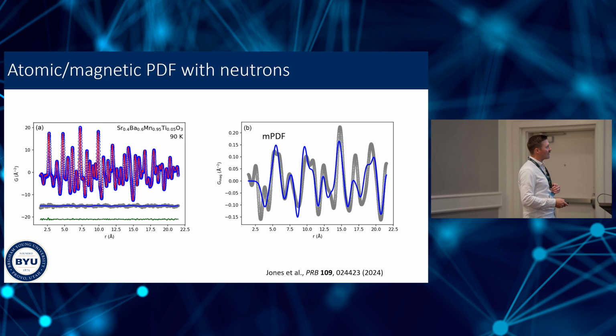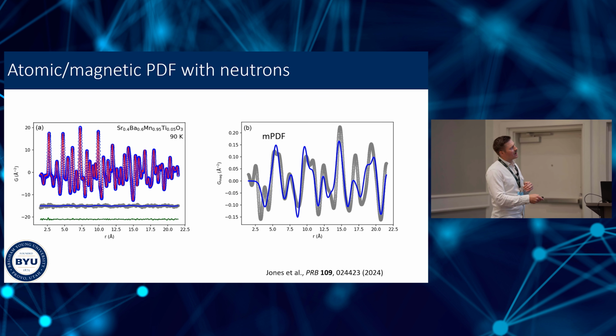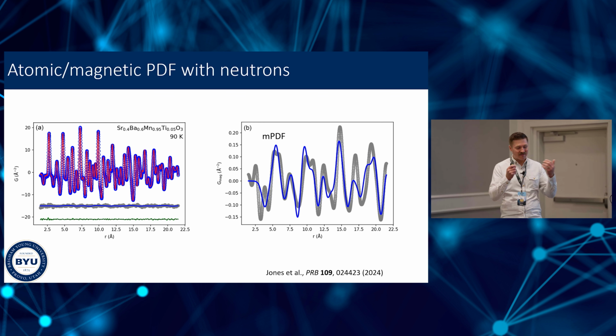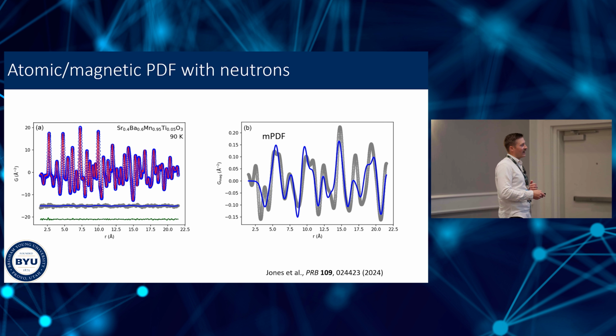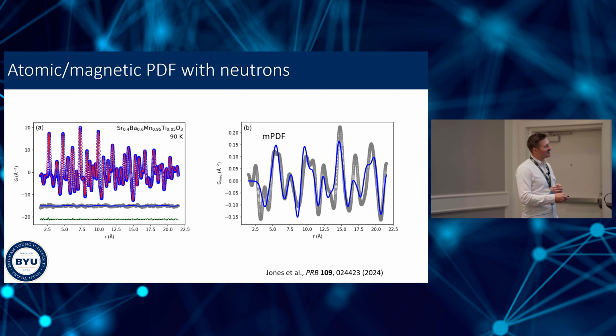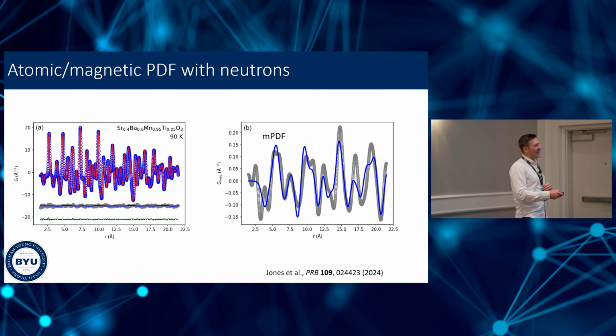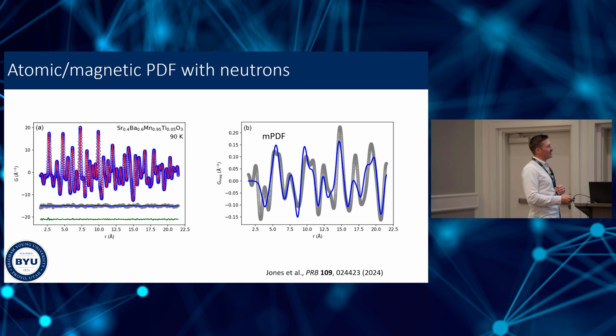Let's prove that more directly by looking at magnetic PDF data. Here's our neutron PDF data for one of the compounds that we looked at. The magnetic PDF signal is actually very small. If you're not looking for it, you won't notice it. So you have to work kind of hard to find it, but if you do work hard and you believe that it's going to be there, then you'll find it. That's not always true, but in this case it was true. We have a small but unambiguous magnetic PDF signal.